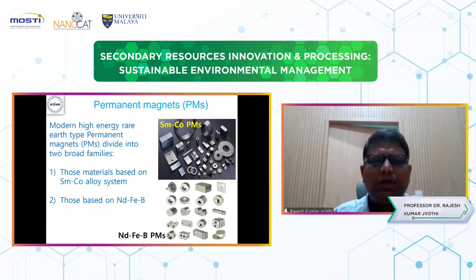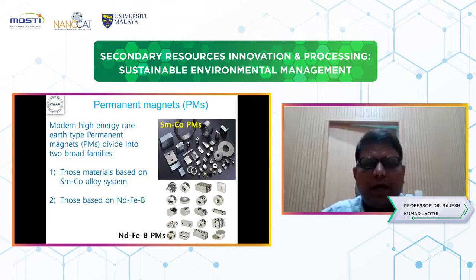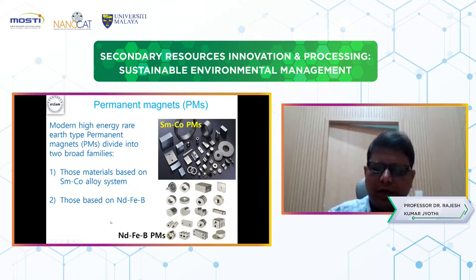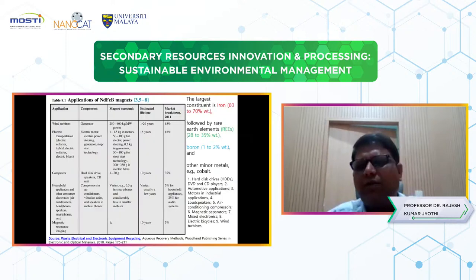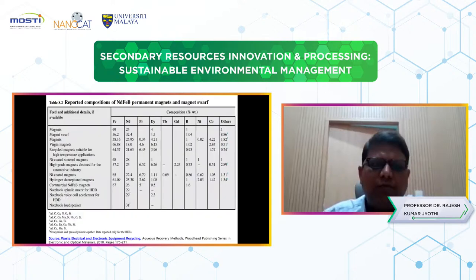You can see here, permanent magnets have two categories. Those are the SmCo alloy system and the NdFeB system. So we are talking about the NdFeB system. The NdFeB system consists of 60 to 70% iron, followed by rare earths at 28 to 35%. Boron is very little, 1 to 2%. Then we can use other metals also. In the NdFeB system we have Nd, Pr, Dy, Tb, Gd, boron, nickel, and cobalt.